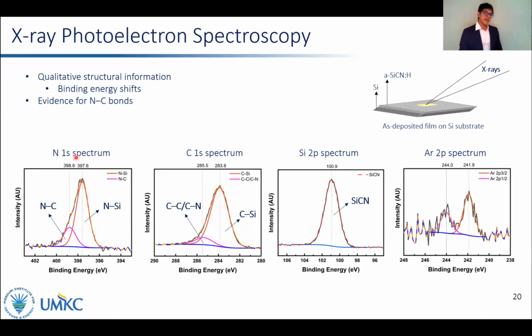For example, the N1s spectrum of XPS was fitted with 2 peaks. One peak corresponded to nitrogen bonded to silicon. The other narrow peak corresponded to N-C bonds. The evidence for the presence of N-C bonds comes only from XPS, because XPS is very sensitive, and this peak corresponds to only 1 to 2% of nitrogen in the overall thin films.